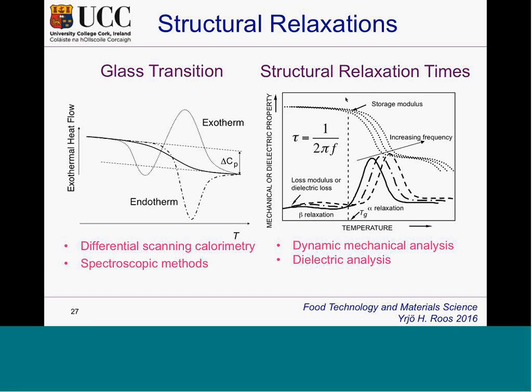So we see the frequency-dependent response of the biomaterial. The higher the frequency, the higher the curve if we measure storage modulus. So that's softening of the material above the glass transition. So at different frequencies we find different values.